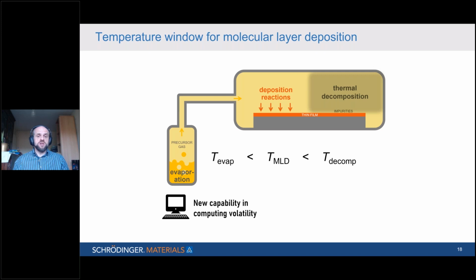So the evaporation temperature is a lower bound, and the decomposition temperature is the upper bound. So if we can adjust those evaporation and decomposition temperatures, we can get a nice wide process window for a successful molecular layer deposition process. And that's where the design process will come in, tuning those different temperatures according to the chemistry that we want to design for. So I want to present our new capability in computing volatility and finding these evaporation temperatures. The lower the evaporation temperature, the more chance we have of finding a successful process in MLD.